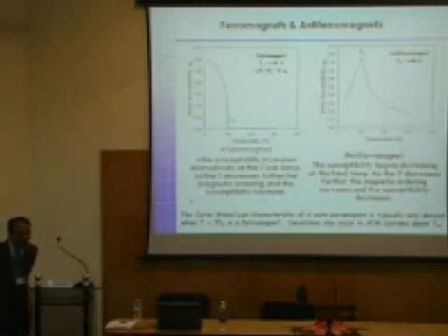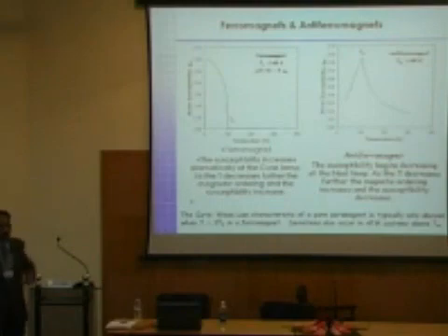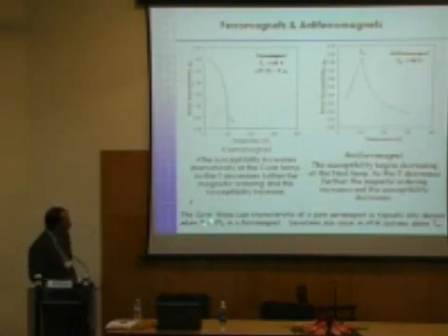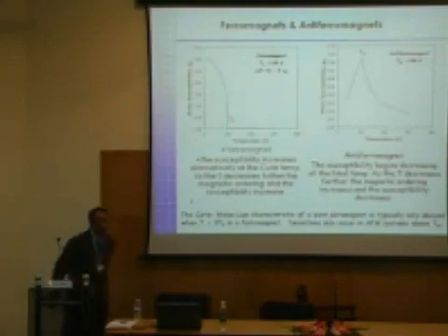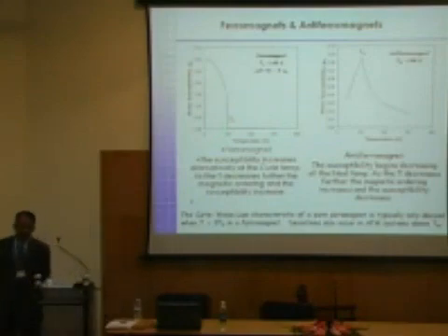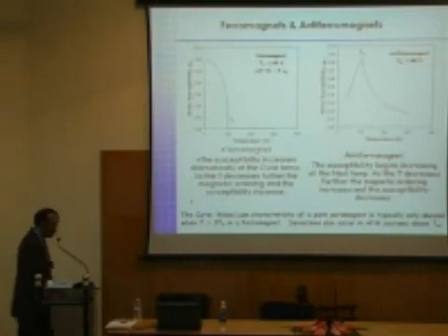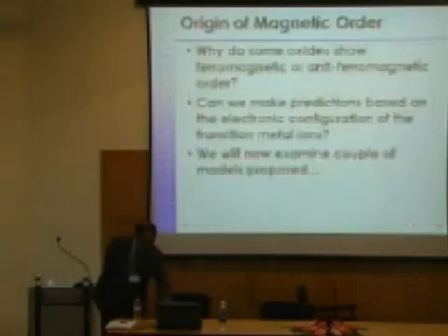Of course, you have to do much more study before you can say that the material is ferromagnetic. I will not have much time to give an extensive lecture on magnetism, but I'm just reviewing some of the fundamental things here. So the Curie-Weiss law, pure paramagnetism, is typically valid only when the temperature of the measurement is 3 times the Tc. So if your ordering is at 100 Kelvin, the sample is truly paramagnetic only above about 300 Kelvin. That is the general rule of thumb that we use in our studies.